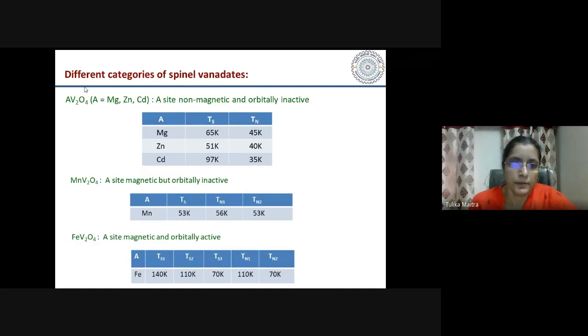Okay, so one can divide these spinel vanadates into different categories depending on the nature of A site ion. If the A site is non-magnetic and orbitally inactive, then we have these compounds, MgV2O4, ZnV2O4, or CdV2O4. Then we see that there is one structural transition and one magnetic transition. The structural transition is from cubic to tetragonal, and there is a magnetic transition from paramagnetic to collinear antiferromagnetic state.